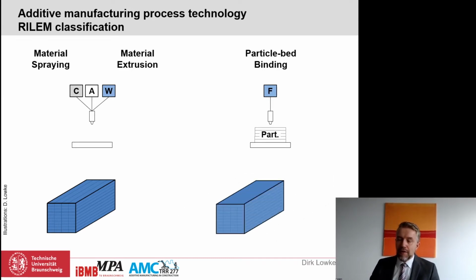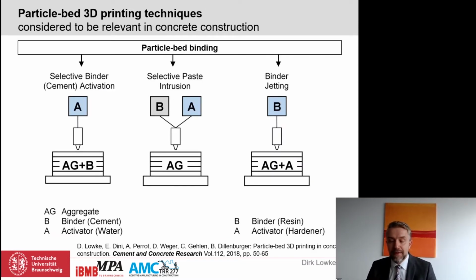If we now have a closer look at the particle bed binding techniques, we can distinguish at least three methods which are considered to be relevant in concrete construction. Firstly, the selective binder or selective cement activation here on the left side. In this technique, the particle bed consists of aggregate and binder, which could be a cement, for instance. And the fluid phase is the activator, which could be simply water in the case of cement as binder. Then we have the selective paste intrusion technique, where the particle bed consists of an aggregate layer, and the fluid phase is a very flowable cement paste.